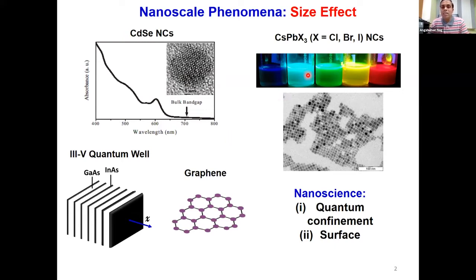And then here, these are the cesium-lead halide nanocrystals. We see different colors because of the different halide ions that have been used. The sizes are about 10 nanometers. And we see the colloidal dispersion because of the surface chemistry of these nanocrystals.